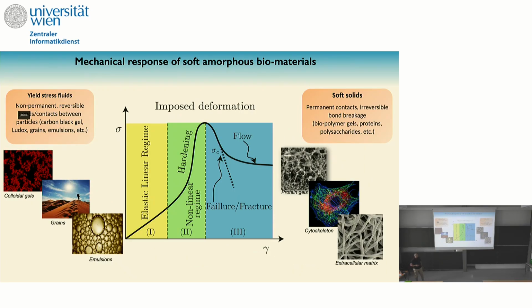So here I'm trying to classify all these systems in this graph, just to summarize the phenomenology or the macroscopic behavior that you find in nature or experiment. Here I'm plotting the stress as a function of the strain, right? As I said before, for all these systems, you would have a linear regime. Then eventually you can get a nonlinear strain stiffening regime. And then after all, the system either would break and you have a failure or fracture, or would flow. And if the system flows, that is a yield stress fluid, you have reversible contacts, so you don't need any external parameter to rebuild your network. This is the case for some colloidal gels, for grains, or for emulsions.